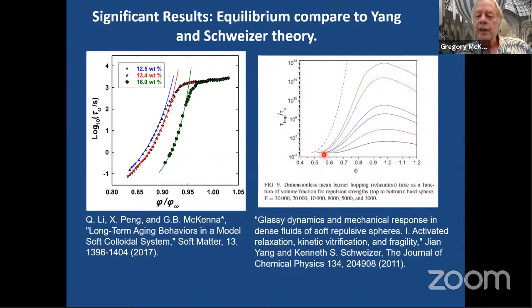And they do see deviations from that at higher concentrations, but also they see what looks like it's going through a maximum, actually. So here we don't get to that maximum. We just get to this plateau, which maybe is like one of these two curves here. And you see again in colloids, what we do see here is we get, in this case, about 4 decades. So that's an actual part of what Ken said, this is not like the 16 decades or something we get with molecular glasses.